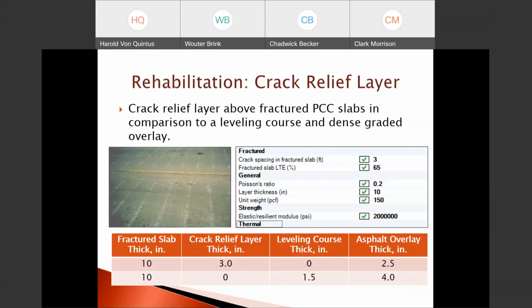And so the table at the bottom shows we have a slab thickness of 10 inches. In one case, we're going to put in a 3-inch crack relief layer of asphalt. We won't have a leveling course, and we'll have a 2.5-inch overlay. The comparison will be not using a crack relief layer. We'll have a 1.5-inch leveling course, and then a 4-inch asphalt overlay. So basically 5.5 inches of new asphalt mix for both cases. The 3-inch crack relief layer plus the 2.5 overlay is 5.5, and the leveling course of 1.5 and an asphalt overlay of 4 is 5.5.